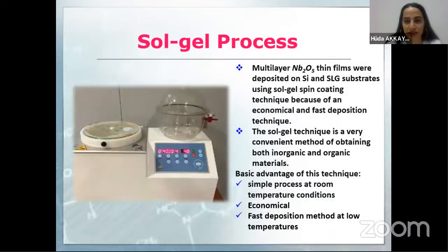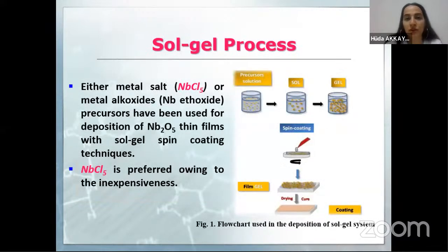This figure shows the Sol-Gel spin-coating system. Niobium pentoxide can be prepared by a variety of techniques, such as electron beam deposition, chemical spray pyrolysis, sputtering, and the Sol-Gel system. In this study, we chose Sol-Gel spin-coating because it has many advantages: 1, a simple process at room temperature conditions; 2, economical; 3, a fast deposition method at low temperatures. The Sol-Gel technique is a very convenient method for obtaining both inorganic and organic materials. The precursors used for niobium pentoxide are 1, metal salts, for example niobium pentachloride, and 2, metal alkoxides, for example niobium ethoxide. If you ask why we chose niobium pentachloride, I say it is cheap.